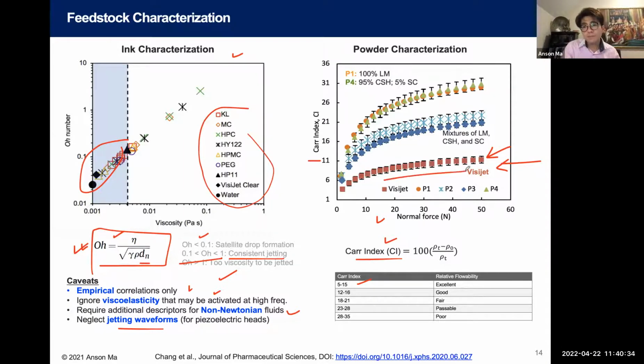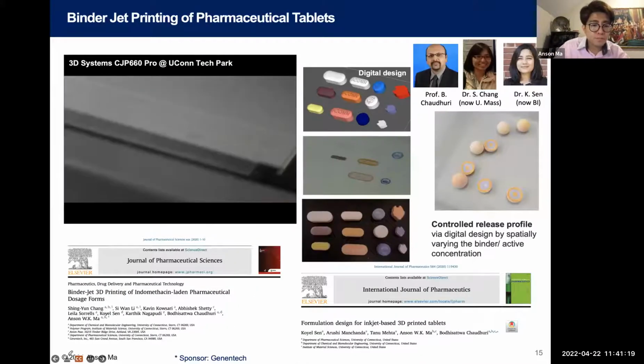So you can see this commercial sample, by manipulating the particle shape and size distribution, has very good flowability because again, the smaller the Carr index, the better the flowability. And then if you look at some of these samples, we have some other formulations that we tried to adjust, and the mixture actually is better. This is a mixture of 3 components compared to the original basic component. Again, this gives you a sense: if I have a new application and need to work with a new powder, you may want to do a little bit of this, so that you get a sense of how well your material could be spread based on benchmarking against existing materials.